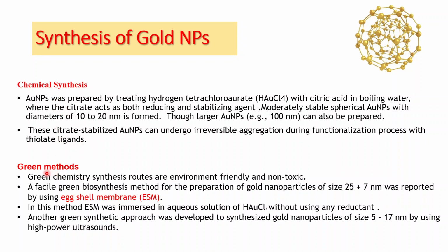And when it comes to green methods, the green chemistry synthesis routes are environmentally friendly and non-toxic. A facile green biosynthesis method for the preparation of gold nanoparticles of size 25 plus or minus 7 nanometers was reported using eggshell membranes. You can see how the gold nanoparticles were prepared using eggshell membranes. In this method, ESM, that is the eggshell membrane, was immersed in the solution of hydrogen tetrachloroaurate without using any reductant. We are only using the eggshell membrane here.